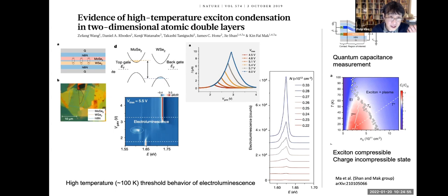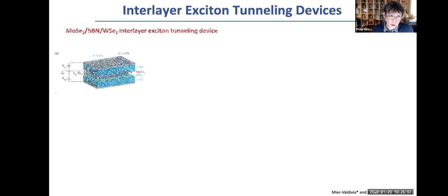Of course, a really direct proof that one can try to make is, can I just look at this interlayer exciton directly and see whether they have some sort of quantumness, quantum coherence, right? So we actually expanded this work even further. Instead of now using a thick layer of boron nitride, we can insert only one atomic layer of boron nitride. That will still give you enough separation between the P and N sides, such that the exciton can live longer.